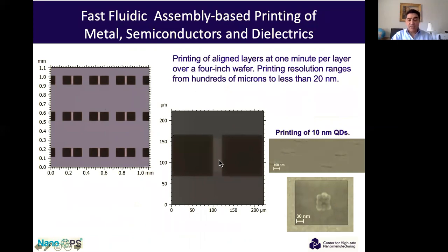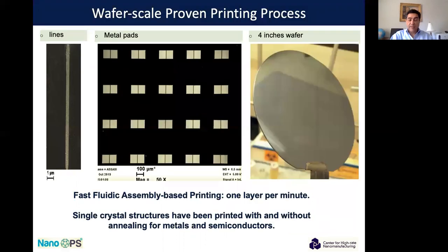And you can do zinc oxide, carbon nanotubes, gallium arsenide, gallium phosphide, zinc selenide, a variety of things. We've also shown that you can do quantum dots. The scale here is 30 nanometers. These are 10 nanometer quantum dots. You can assemble them exactly where you want. So that's a very powerful process that allows you to do a lot of things that are very difficult or impossible to do using conventional fabrication.